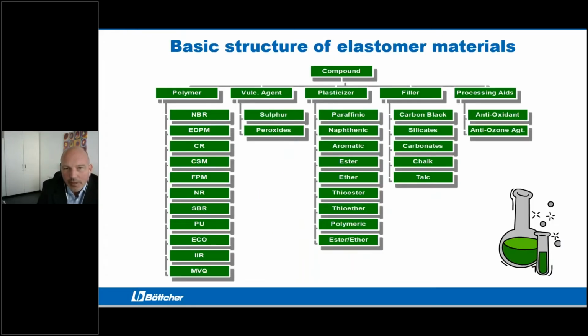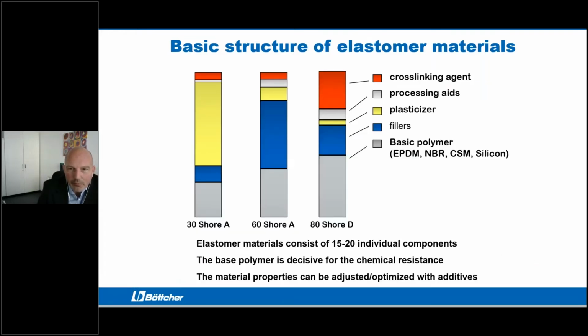The basic structure of an elastomer material: for example, some of you may know that we call it an EPDM with 60 Shore, but EPDM is not only one basic polymer. Normally, the coverings are made out of a recipe, and this recipe contains up to 15 to 20 different ingredients. This can be the polymer like EPDM or NBR, but there are also vulcanization agents like sulfur or peroxide. We need some plasticizers, we need some fillers, and also anti-aging and processing materials inside. So this means the elastomer covering is made out of 15 to 20 different individual ingredients.